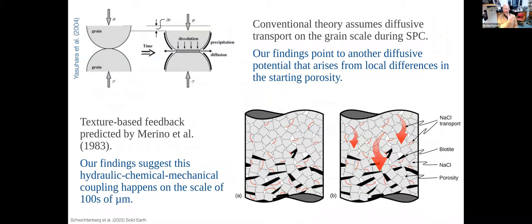Because what we think this proves is that the theory is wrong. Remember, I made quite a big point at the beginning to say that the dissolved salt just moves around the corner and gets reprecipitated. What we have identified is obviously material transport, salt transport, on distances which are significantly greater than individual grains, by a factor of 50 or so. So obviously there's another driver, another pull for the salt. And